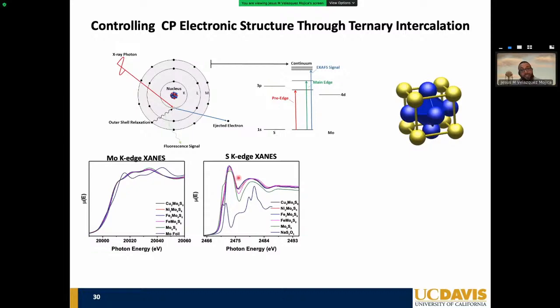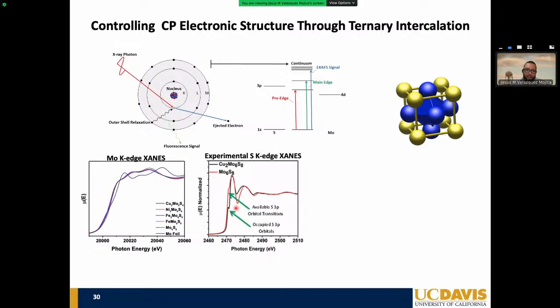Now, when you look at the sulfur K-edge, it's a little different. If you again focus on the pre-edge region of those intercalated Chevrel phases, there are some bumps and bruises there. And upon closer look, when you focus on the red X-ray absorption spectroscopy pre-edge region, there is this nice little shoulder here. This shoulder has been ascribed, by theoretical work by David Prendergast and some of the magnesium intercalation work experimentally, to available sulfur 3p states. Once you intercalate something like copper, you depress this feature to have a smaller shoulder. And actually this feature could completely disappear if you completely occupy the available sulfur 3p orbitals.